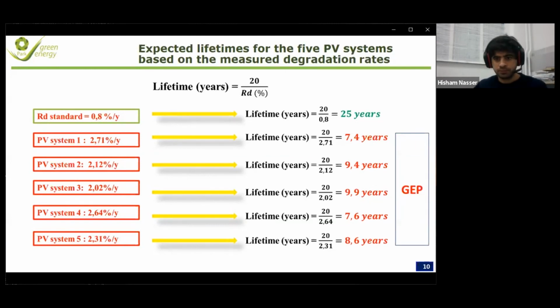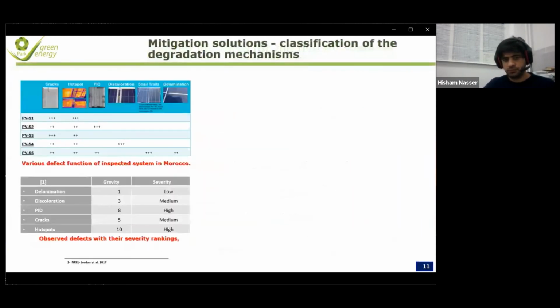This is by mitigation of the real observed degradation in Morocco and the different observed degradation modes in the Green Energy Park. So our next step will be the proposition of some solutions for a desert PV module based on the observed degradation modes in Benguerir, Morocco. So, in order to further quantify the results of the analysis of the Moroccan degradation modes, we consider a classification based on the severity of the different observed degradation modes.